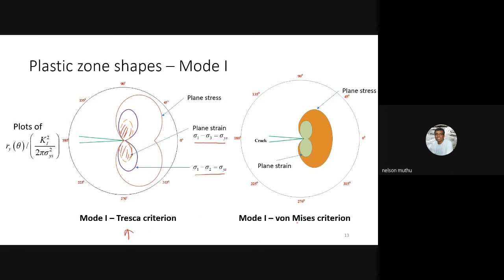Whereas if you use the von Mises criterion, that is straightforward. For plane strain, this is the size of the plastic zone. For plane stress, it is comparatively higher. Again, you have to note that these are all normalized values: ry of theta by K1 square by 2 pi sigma y square.